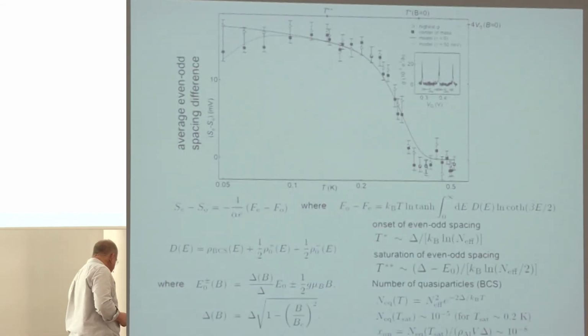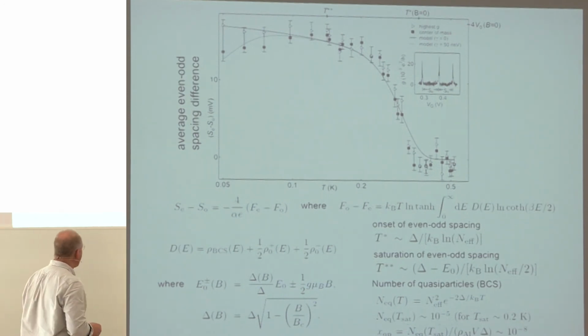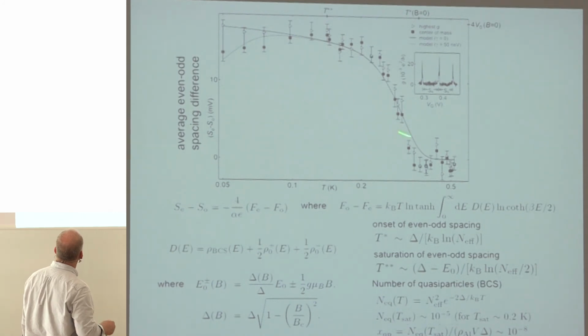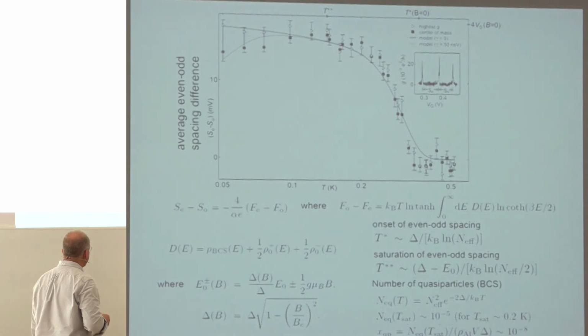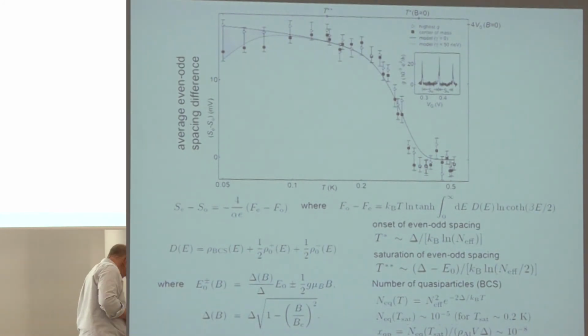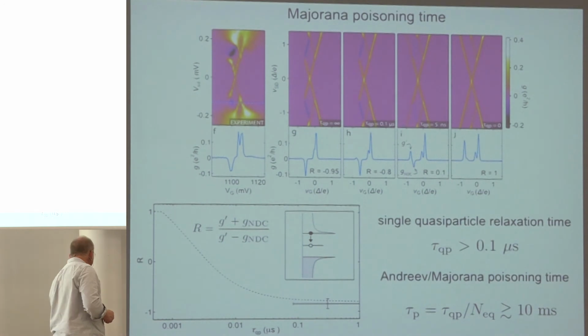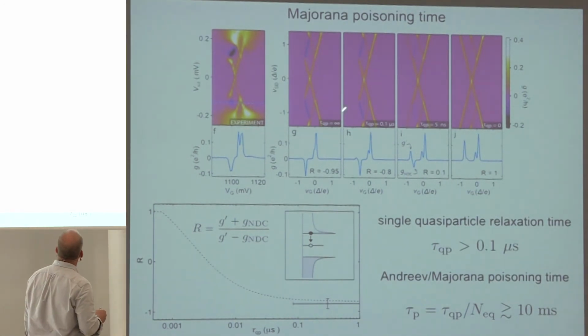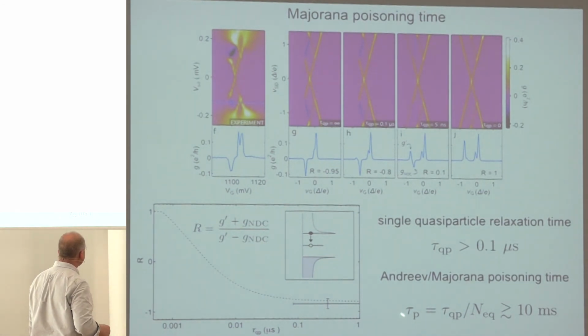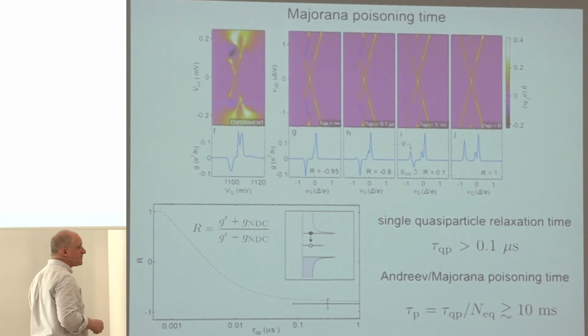And if we do the full thermodynamics of how those states are occupied, I will spare you the analysis here, you see that the data follows the curve very accurately, and that analysis allows us to calculate the number of free quasiparticles. And by finally finding the relaxation time based on the strength of that negative differential conductivity, we can find the characteristic relaxation time from the BCS density of states down into this Andreev state, and call that characteristic time the poisoning time.